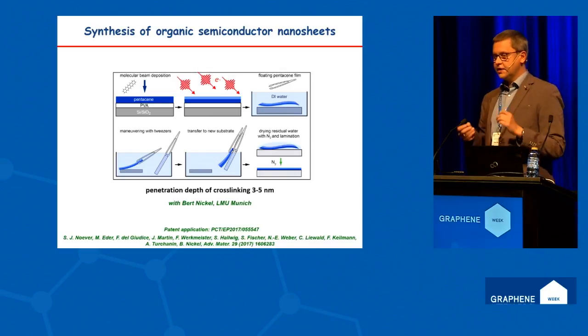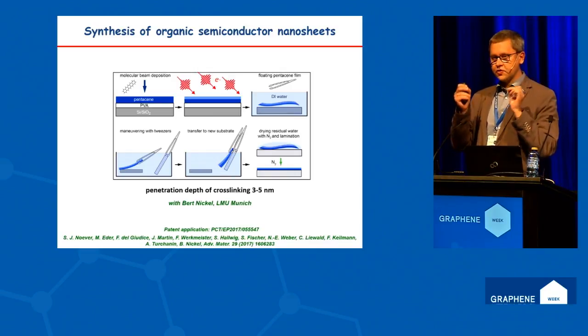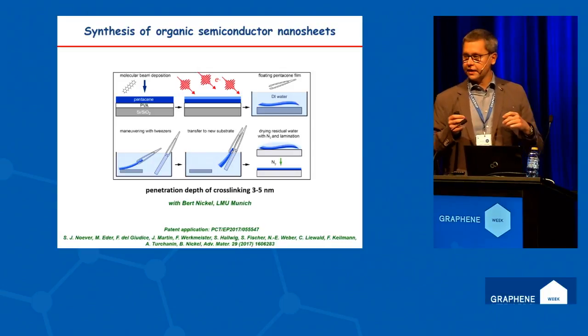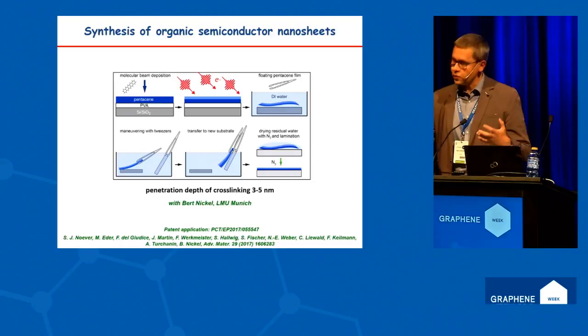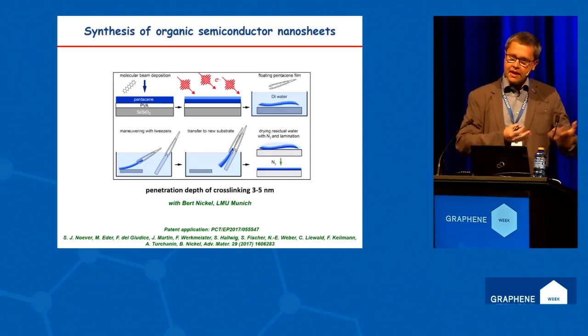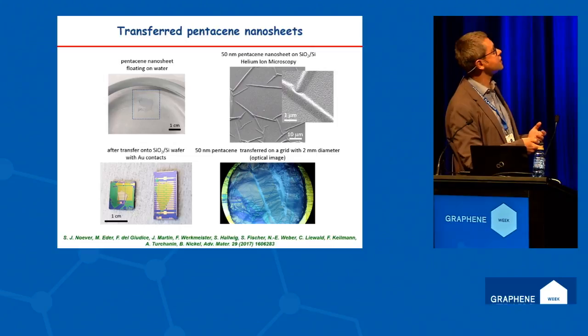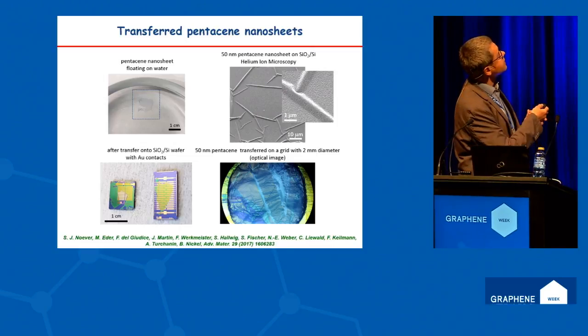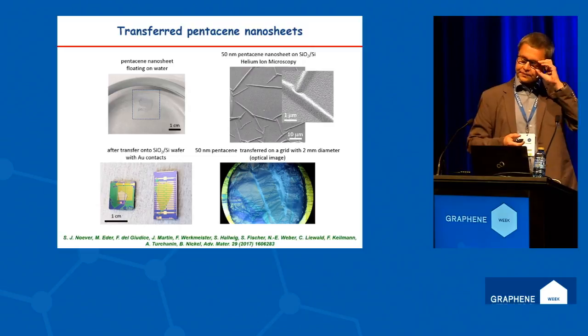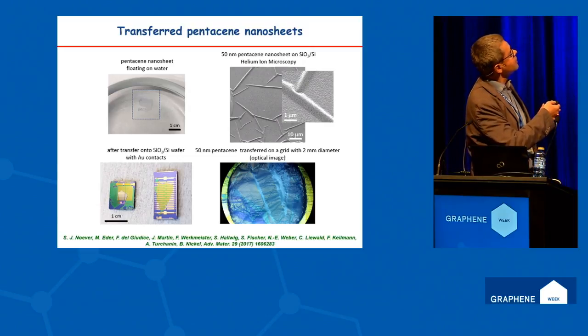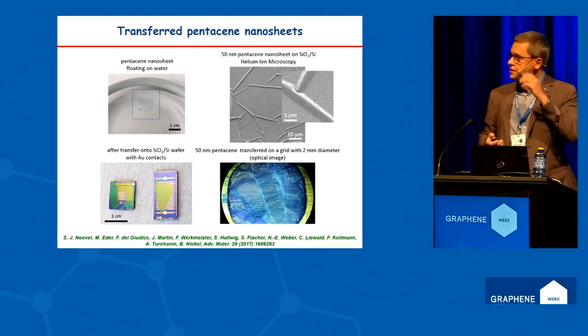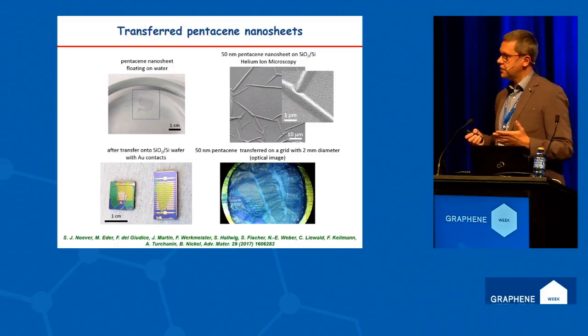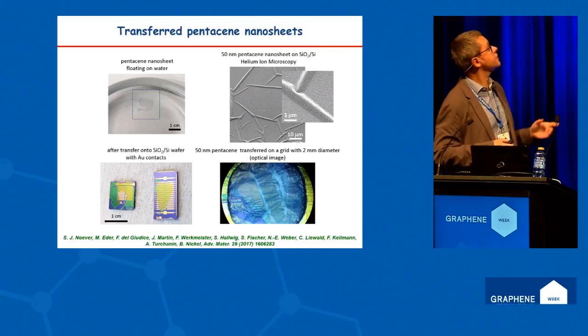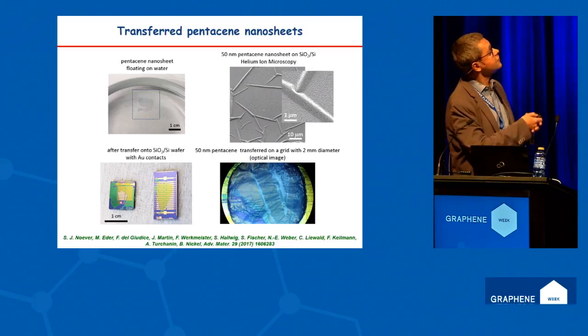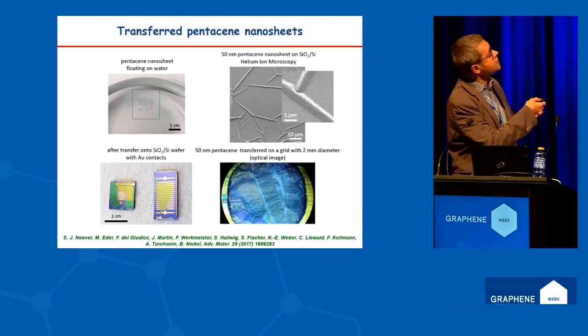which corresponds in the case of pentacene molecules to only 3 atomic layers. And in this case, this cross-linked layer works like a carpet backing, stabilizing the whole system and enabling us to make a new kind of nanosheet of this organic semiconductor. You see the example here, organic semiconductor sheets floating on top of the water. You don't need any stabilizing layer like PMMA, which you use for other two-dimensional materials, because this film is stable enough.